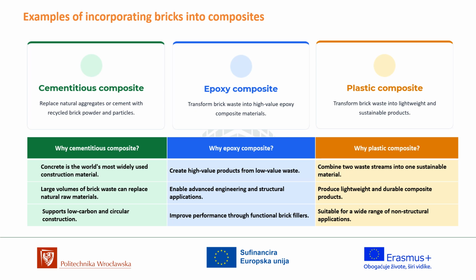For example, cementitious composites. Since concrete is the most widely used construction material globally, integrating brick aggregate here allows us to absorb massive volumes of waste. By substituting natural virgin aggregates or cement itself with fine brick powder, this path directly lowers the carbon footprint of concrete and seamlessly supports circular construction on a large scale. In the case of epoxy composites, this pathway focuses on value creation, turning low-cost crushed brick waste into high-value engineering materials. By using ceramic particles as functional fillers in epoxy matrices, we enhance mechanical performance and enable specialized high-strength structural and repair applications as well.